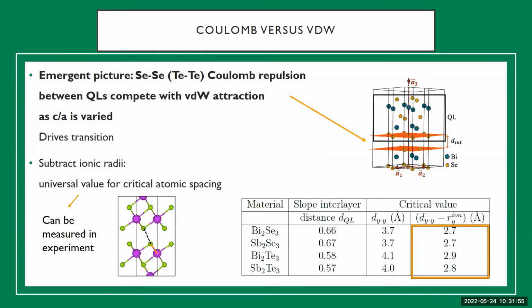But the emergent picture that we found was that it was basically the Coulomb repulsion between adjacent quintuple layers, which competed with the van der Waals attraction between them. And this competition was basically driving the transition.